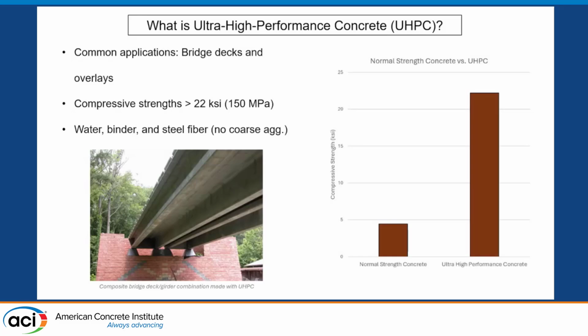The applications for this are because UHPC has a very low water to binder ratio, and so this causes it to have a very low porosity. When used in a bridge overlay, this means that water and salt from a salt truck can only penetrate so far from the surface, and therefore rebar or steel reinforcement is less likely to get corroded. And so the maintenance cost over time is significantly decreased compared to normal strength concrete.